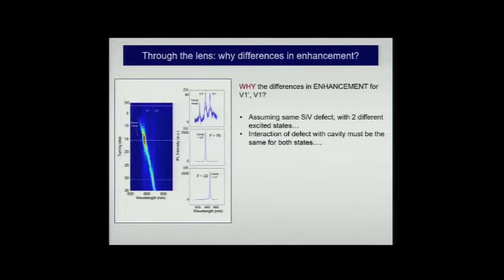Why should the amplification be different? The cavity has the same properties. The defect is presumably in the same position in the cavity, so it sees the same local high electromagnetic field. What is different? Why should I see a factor of 75 increase for one transition, that is to the higher energy excited state, and only 22 for the lower energy excited state?